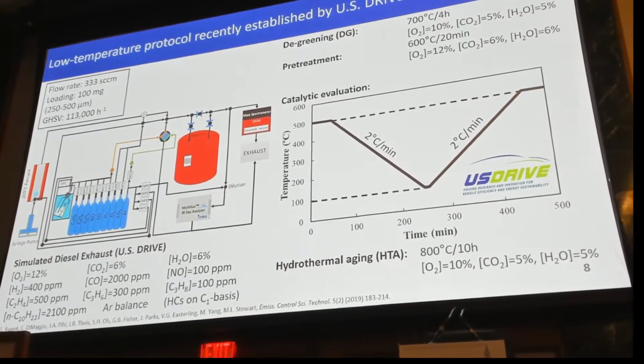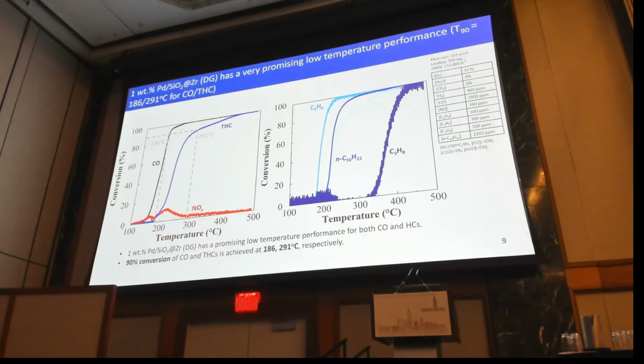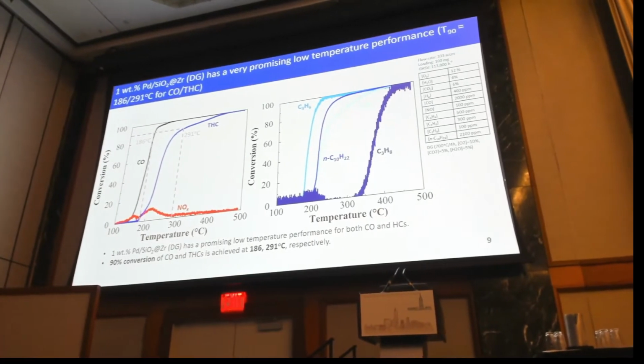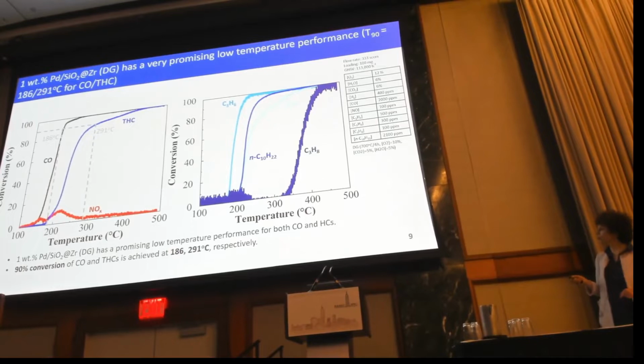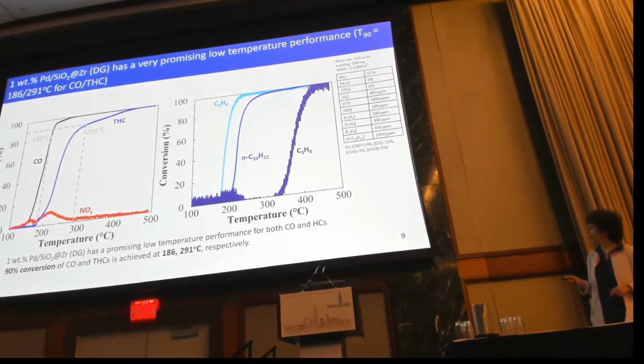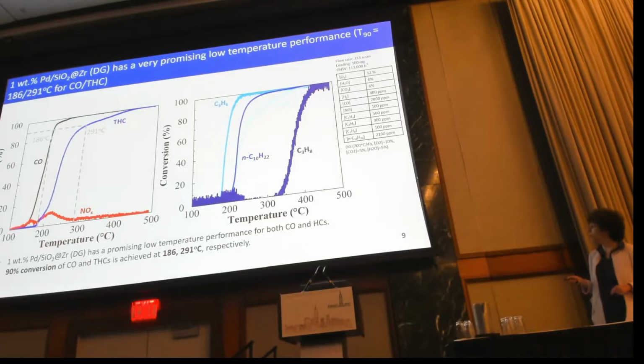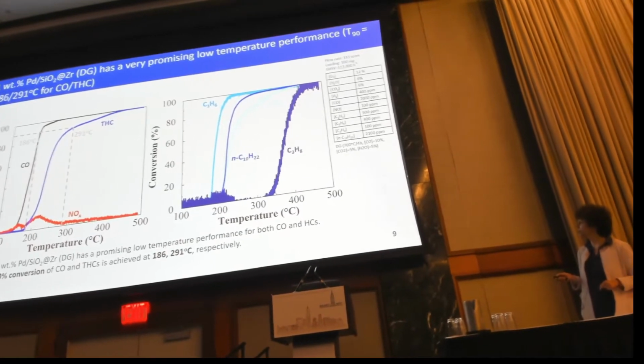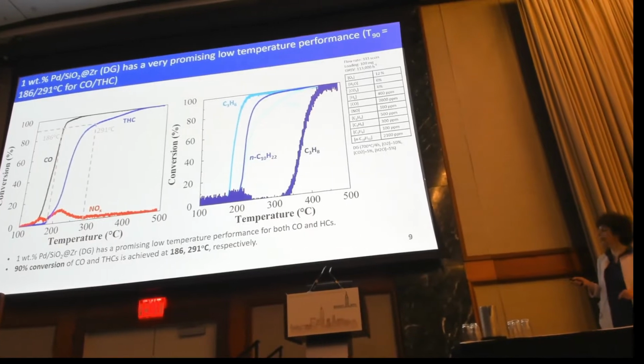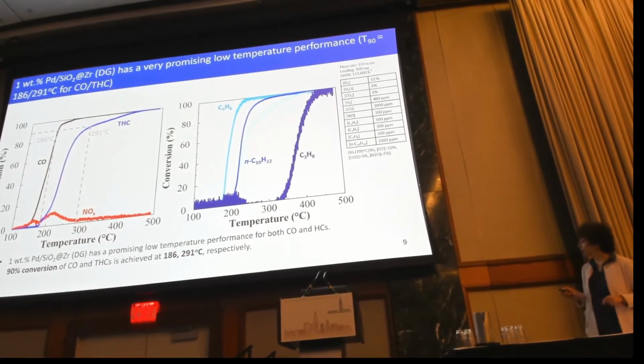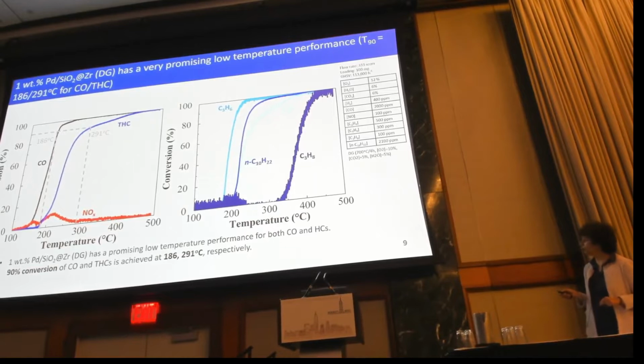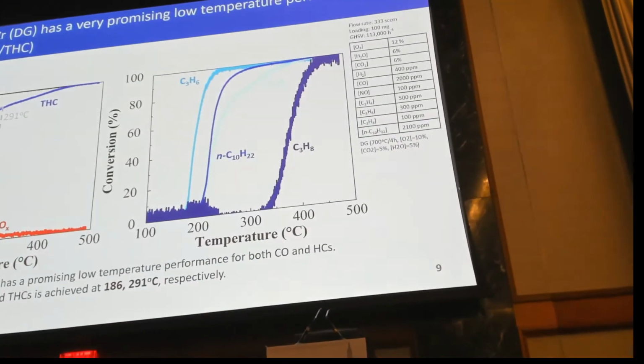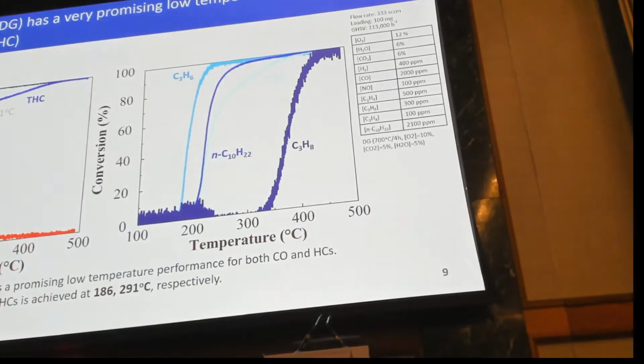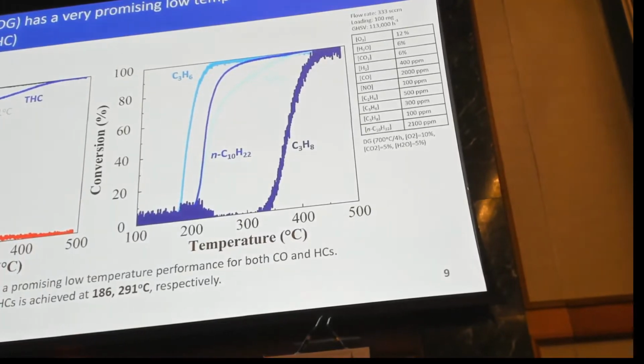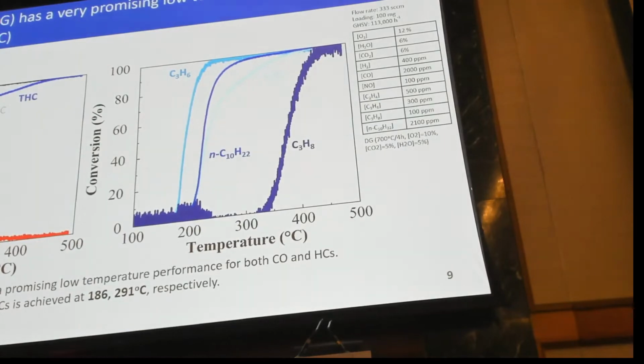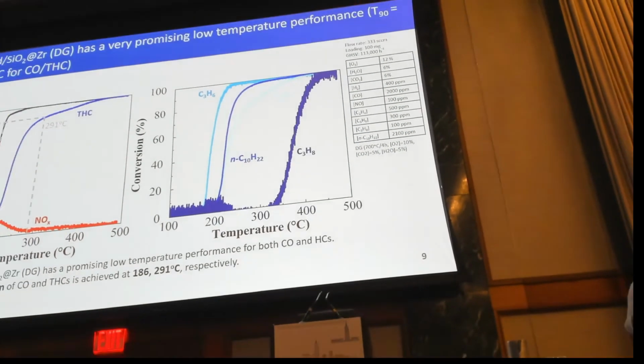So let me show you the performance of the degreened monometallic palladium supported on the zeolite support. The left figure here shows the CO in black, total hydrocarbon in blue, and the NOx conversion as a function of the temperature. And then the right plot shows the hydrocarbon conversions only separately. So what we see here is that this material can achieve 90% conversion of CO at around 186 degrees C, 90% conversion of total hydrocarbons at around 291 degrees C, and NOx is not converted.